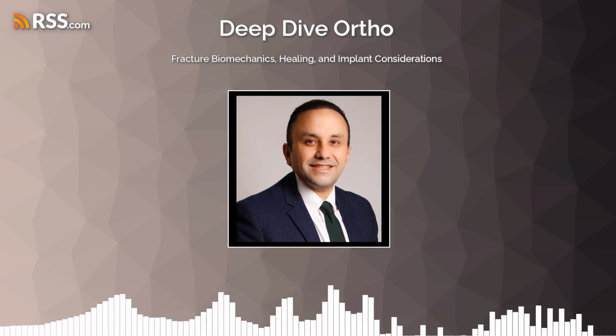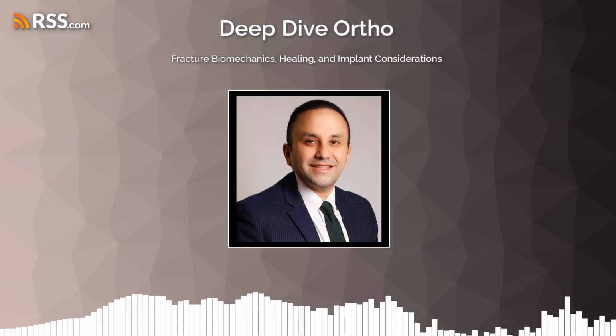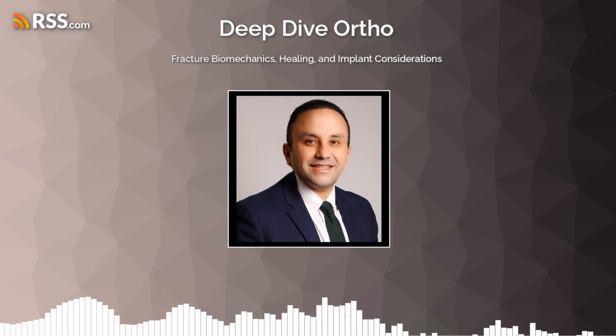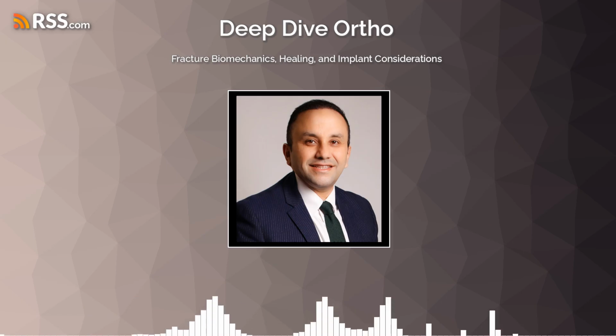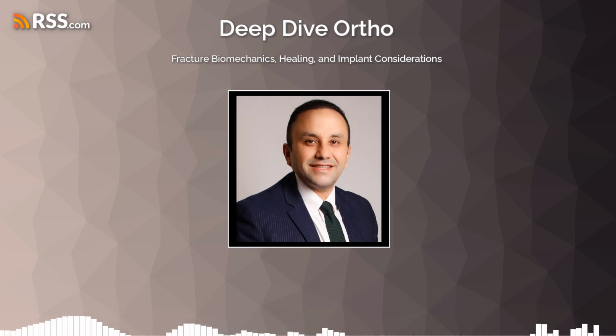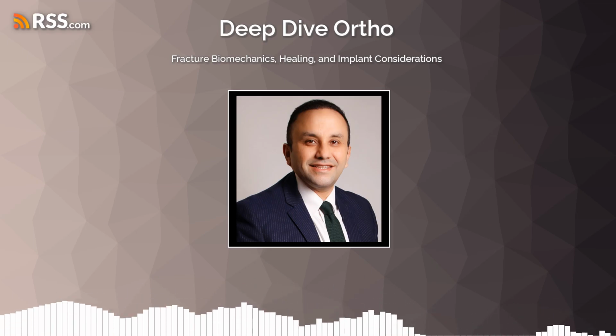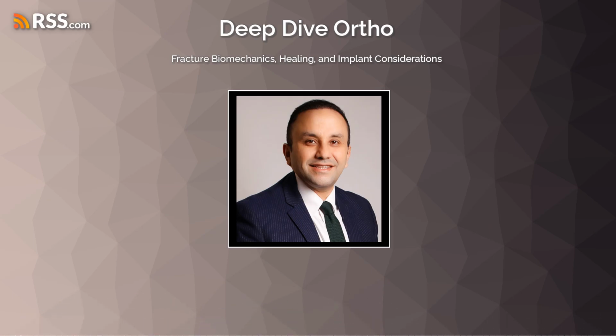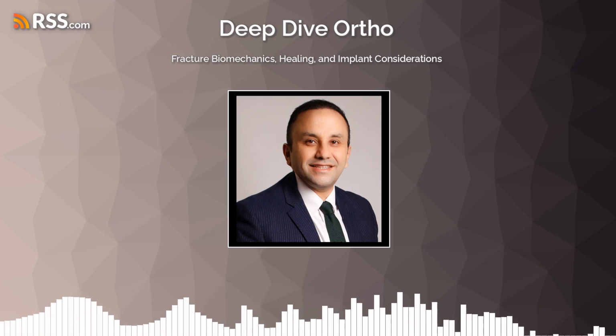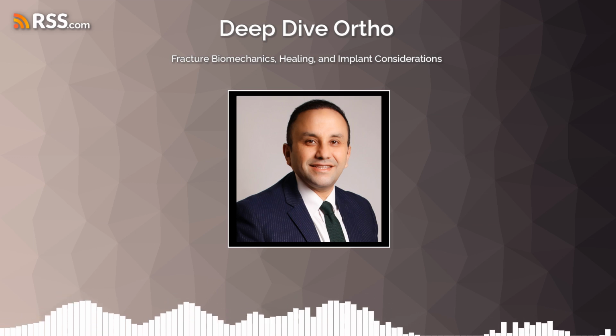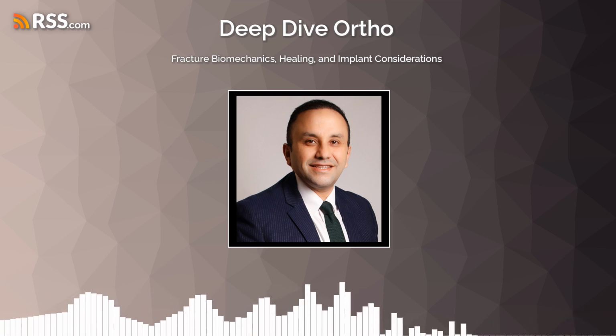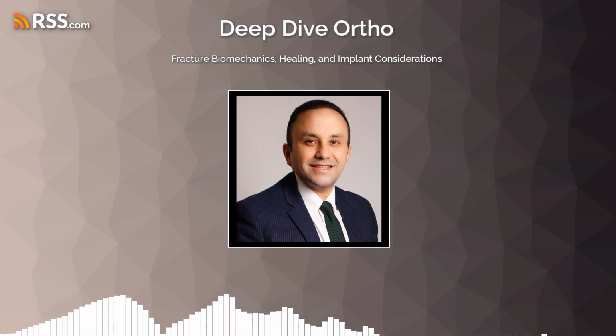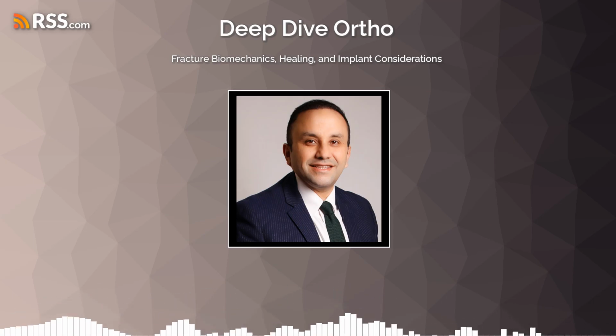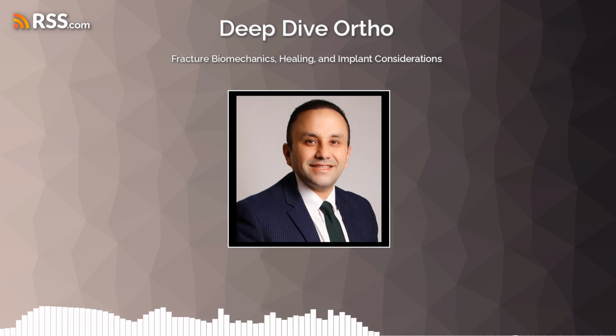But certain conditions can break down this protective layer. You can get galvanic corrosion if two different types of metals are in contact within the body. Like mixing steel screws with a titanium plate. Precisely. That's generally avoided. Then there's fretting corrosion caused by surface damage due to microscopic motion between implant components, like a plate and a screw head. Crevice corrosion can happen in tight, low-oxygen spaces, again, like under screw heads or plate interfaces. Pitting corrosion is localized breakdown, maybe from surface abrasion. And stress corrosion is where a crack in the metal is accelerated by the corrosive environment.